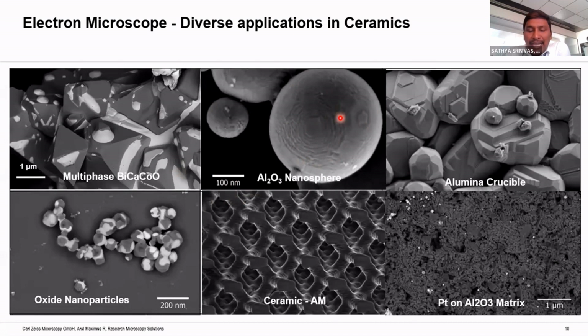If you apply higher kV, as you know, the higher the kV, the better the resolution, right? But if you apply higher kVs for such samples, it is very difficult to focus and very difficult to get these images. So the system should be capable of picking up a higher resolution at lower kVs. This is one of the best examples of such a low kV application. And here you can see the contrast difference, right? The contrast difference itself through electron microscopy, even with the imaging, is called material contrast.